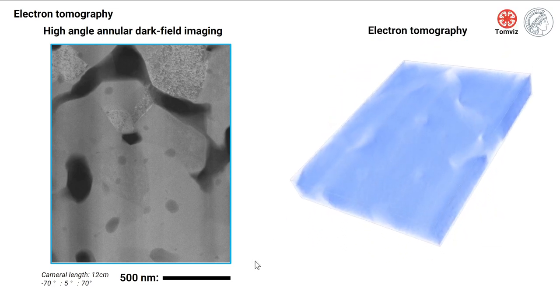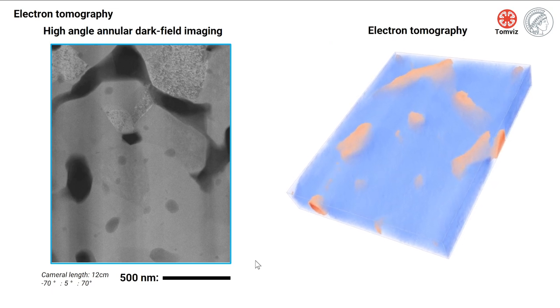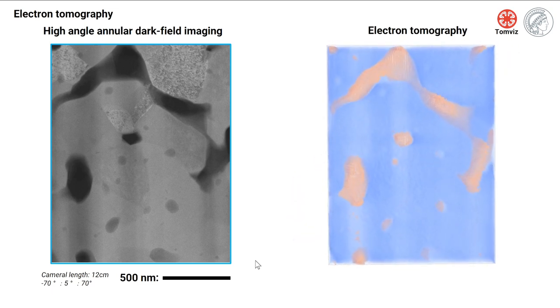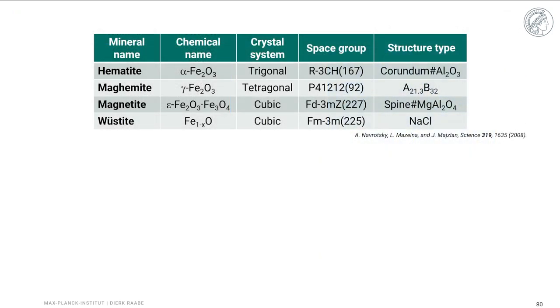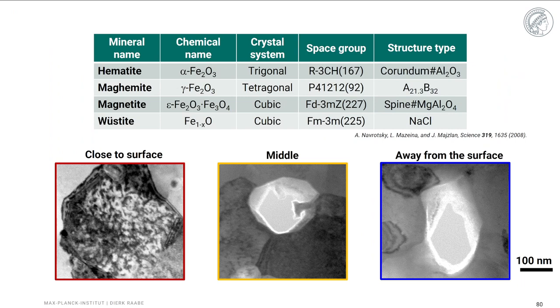And you can see that many of these pores are actually highly isolated. That means they are not connected, so that the water that forms on the inside of these pores cannot leave the material but stays in the material. And that is quite interesting.